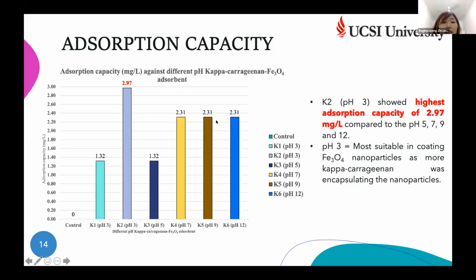We can also measure the adsorption capacity from the treatment. K2 with pH 3 showed the highest adsorption capacity of 2.97 milligram per liter compared to the other pH 5, 7, 9, and 12. pH 3 is the highest because the iron oxide is positively charged, and the Kappa-carrageenan is negatively charged, so they will bind nicely by electrostatic attraction at pH 3.